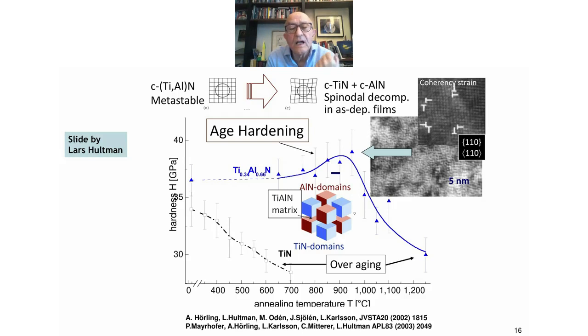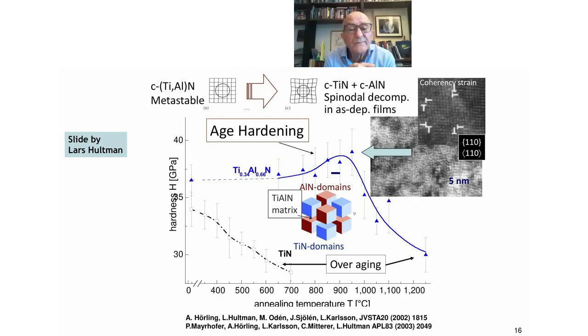As aluminum nitride tends to, like spinodal decomposition, accumulate in areas, the lattice gets strained, and that causes hardening. The TEM picture is actually a micrograph of such spinodally decomposed cubic titanium aluminum nitride. You see this checkerboard pattern with roughly 2 nanometers periodicity. Then at higher temperatures, dislocations appear, and the aluminum nitride regions switch to the wurtzite phase, which is soft, and there is this overaging. So the hardness drops due to the phase separation. Next slide.